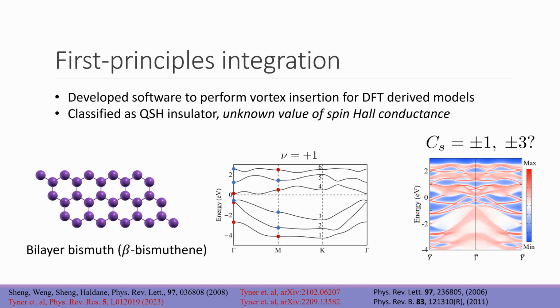So seeing how well this flux tube insertion worked to probe for this non-symmetry indicative topology, we went about trying to see if we can use this in realistic band structures. And to do that, our proof of principle was bilayer bismuthene. We chose this because there's some nice early work, 2006, 2011, from the group of Murakami, where they looked at the occupied ground state and assigned it a non-trivial Z2 index, saying it's a spin Hall insulator, but they couldn't determine whether the spin Chern number here should be of magnitude 1 or magnitude 3.